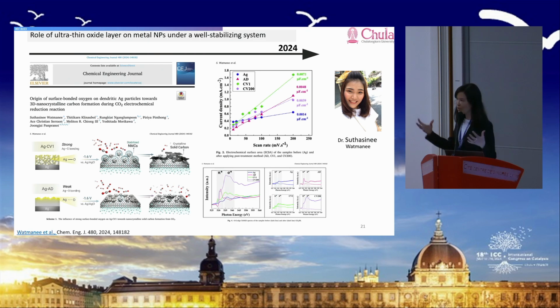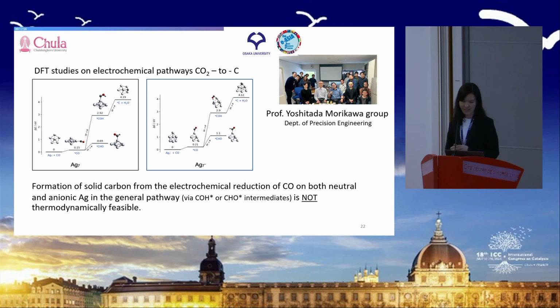If you have too much of the oxide, this won't work. If you have too little, it also won't work. And now, with our collaborators from Osaka University, we try to look into the pathway for CO2 to carbon. People have looked it up already, and neither is thermodynamically feasible, either via COH or CHO. So CO dissociation into carbon is not feasible via the electrochemical pathway.